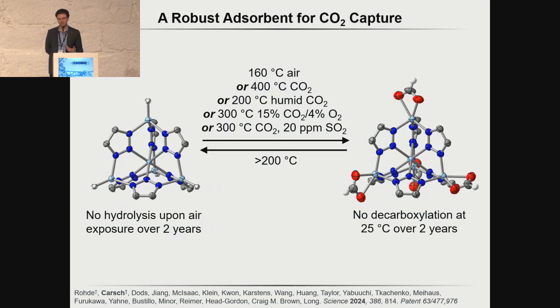Well, this is quite a remarkable material. We can take our zinc hydride, expose it to CO2, and it makes a zinc formate species. We can capture CO2 from air at elevated temperatures. We can capture at 400 degrees Celsius. We can tolerate water vapor at 200 degrees, although above 200 degrees, this is the current limitation of this material. And we can tolerate oxygen and SO2. And once we make this zinc formate material, simply by elevating the temperature and dropping the pressure, we can strip this material of CO2. And that's something that we're really quite excited about.